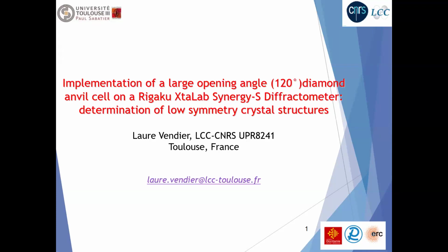XRD under high pressure. So the goal of my presentation today is to demonstrate you that it is now possible to carry out studies under high pressure with very good quality results, publishable results, on a home diffractometer. So in our case, this is a Rigaku, the Synergy XtaLAB, even without being basically specialist in high pressure. And thanks in particular to the very good usability of the diffractometer, of the Synergy, and of its associated softwares, CrysAlisPro and CrysAlisRed. Thanks to the implementation of a large opening angle diamond anvil cell, 120 degrees, on this diffractometer, we succeed to determine and refine low symmetry crystal structures.